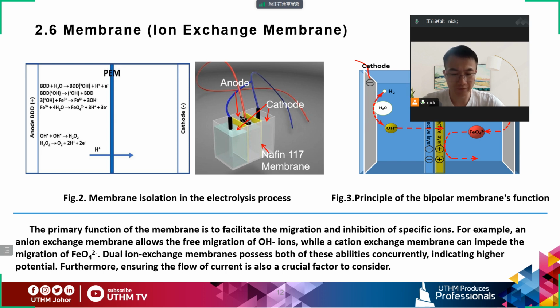The primary function of the membrane is to facilitate the migration and the inhibition of specific ions. For example, an anion exchange membrane allows the free migration of the hydroxide ion, while a cation exchange membrane can impede the migration of FeO4^2-. Dual ion-exchange membranes possess both of these abilities concurrently, indicating higher potential. Furthermore, ensuring the flow of current is also a crucial factor to consider.